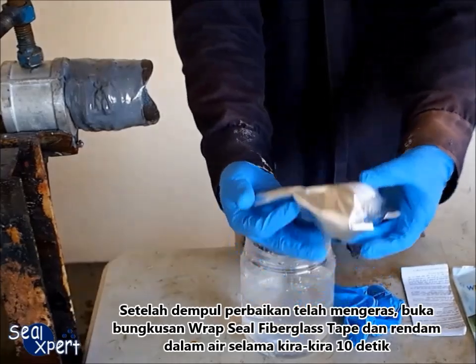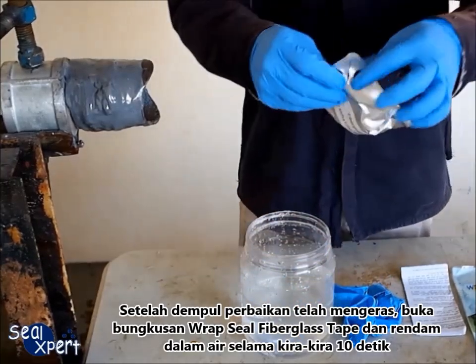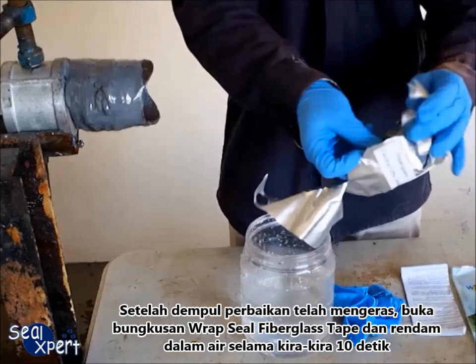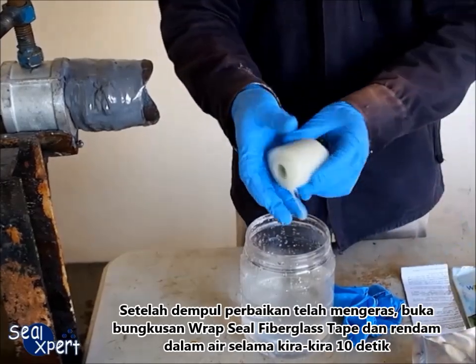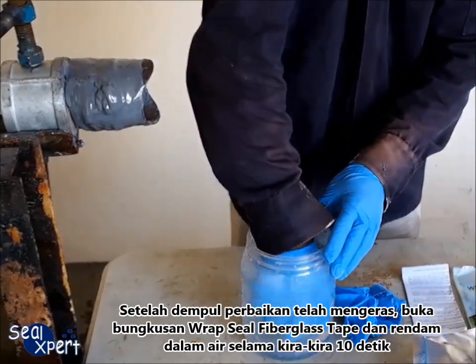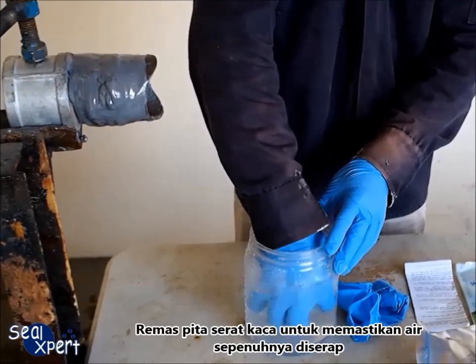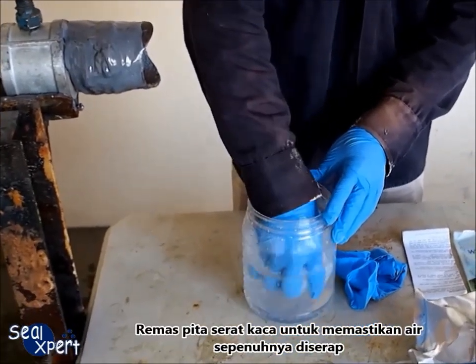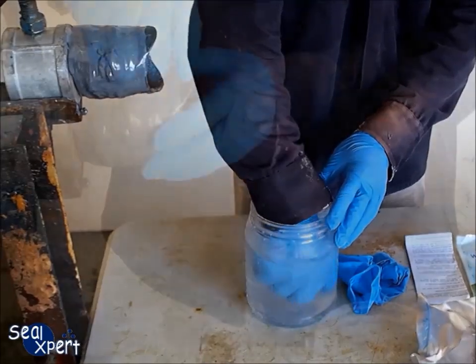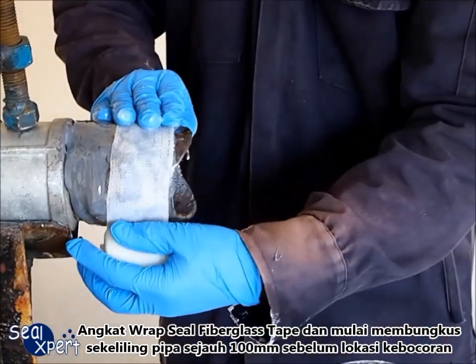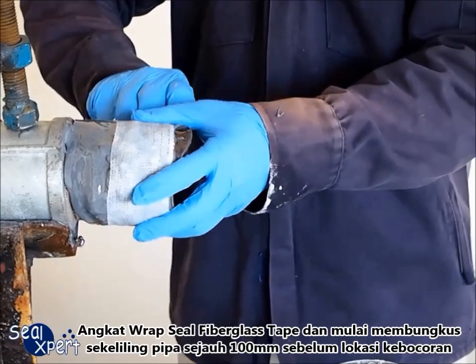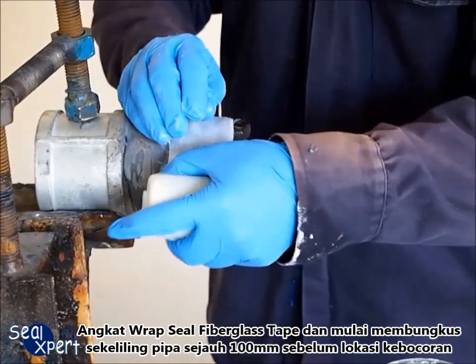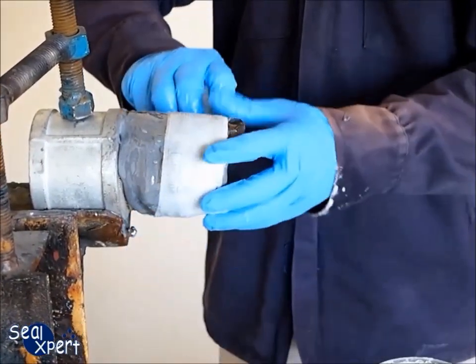After the repair putty has been cured to the required time, open the pack of wrap seal fiberglass tape and soak in water for about 10 seconds, squeezing the fiberglass tape to ensure water is fully immersed. Remove the wrap seal fiberglass tape and start wrapping around the pipe at about 100 mm before the leak location.